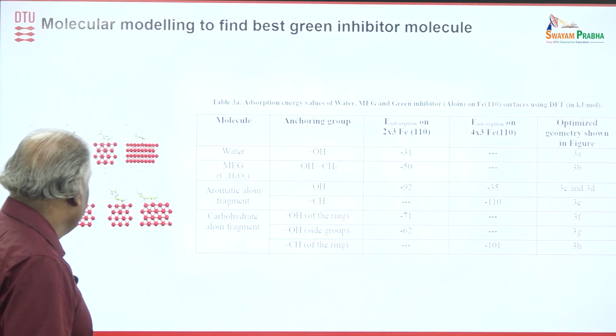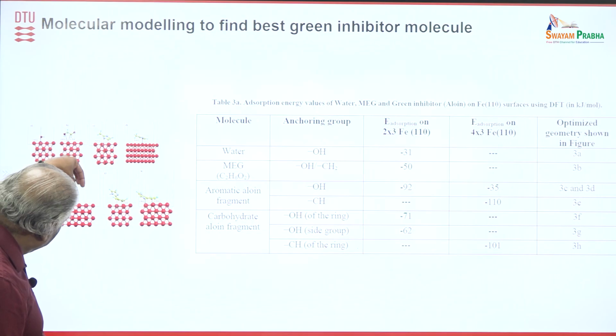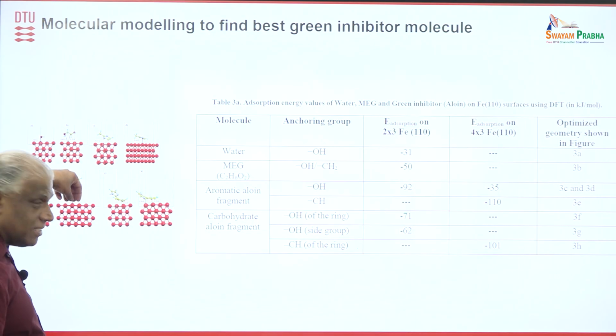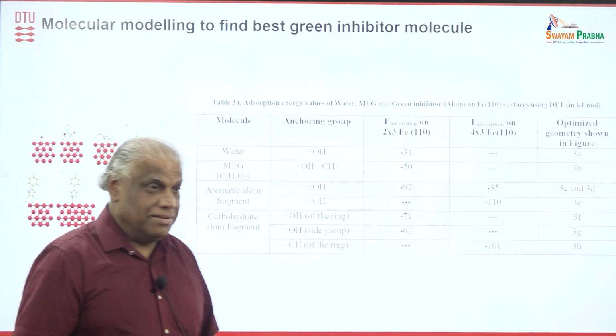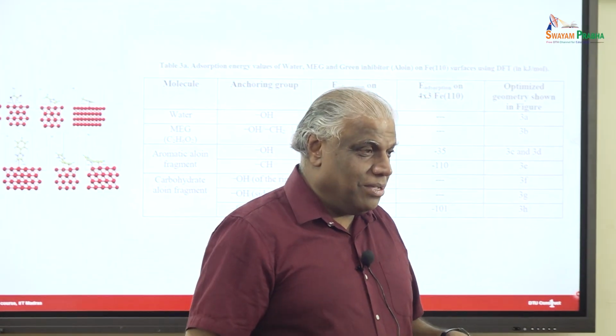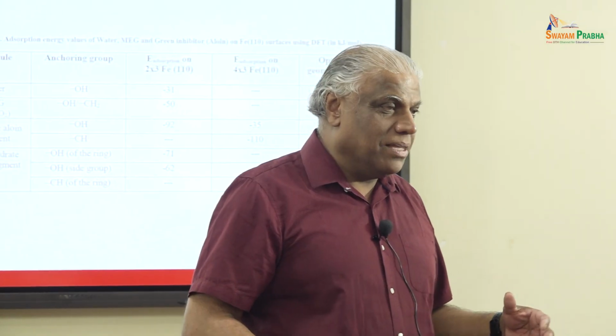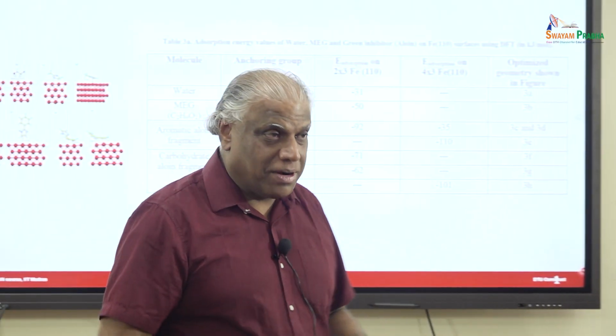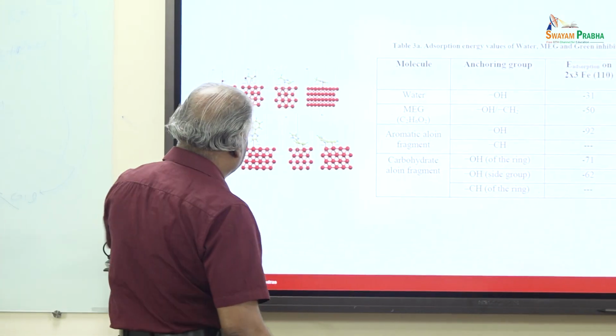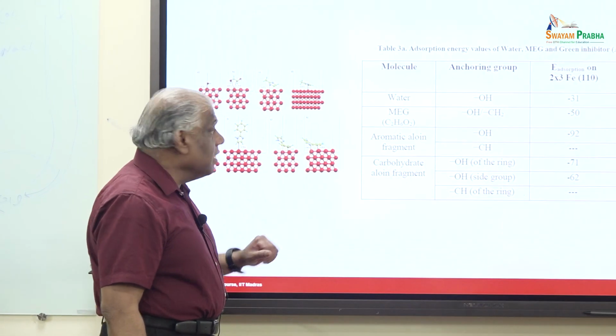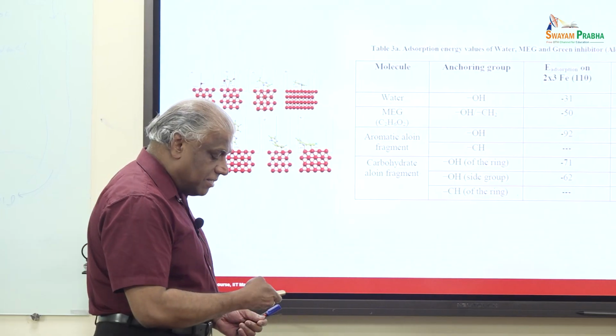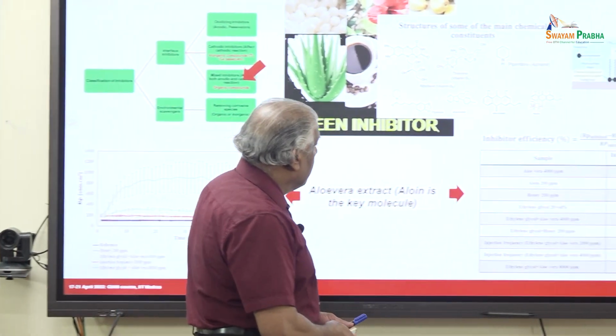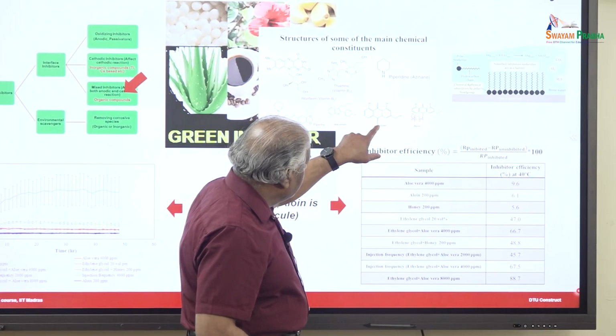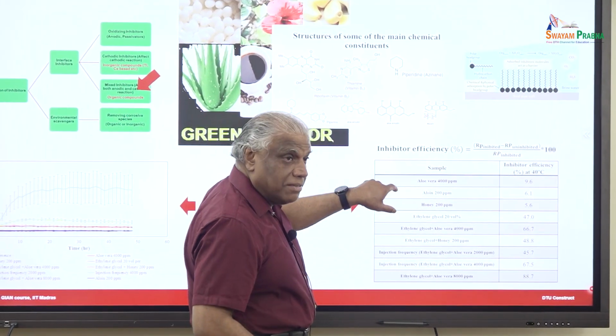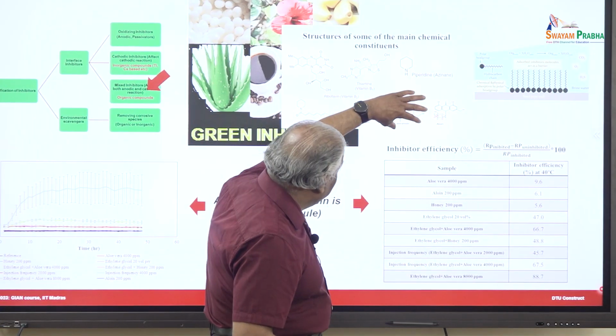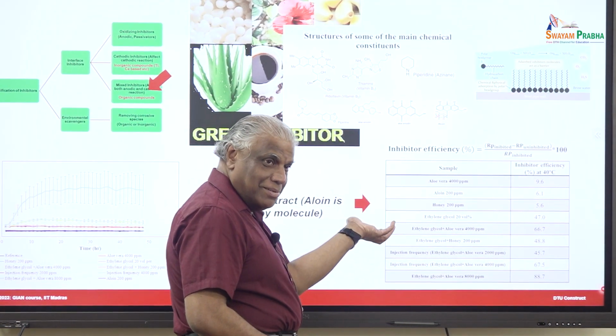So you take the iron, and this molecule is coming to the surface and is adsorbing onto the metal surface. What is the energy of adsorption? This we can calculate by using these molecular modeling programs. We can calculate the adsorption energy of this molecule. Not only that, if you take this molecule, there's an oxygen here, so it can adsorb like this. There are 3 oxygens here, so it can also adsorb that way. That also we can do.